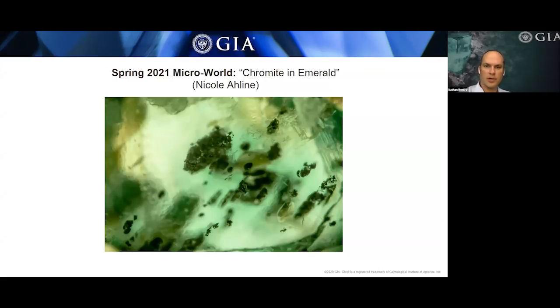Also in the Microworld section, we had several interesting entries, one of which was chromite inclusions in emerald. This emerald was from Brazil. You have all these chromite inclusions, which are basically chromium oxide, and one of the main chromophores for emerald is chromium. What you see here are green color concentrations around the chromite grains. So this is an interesting relationship between the inclusions and the localized green color.